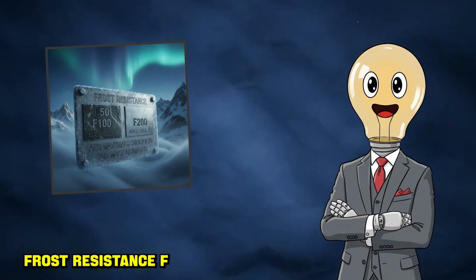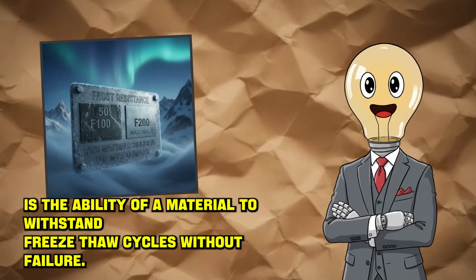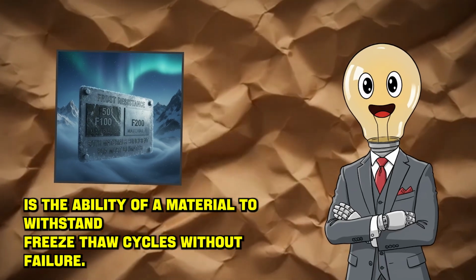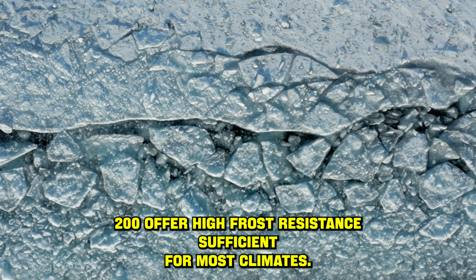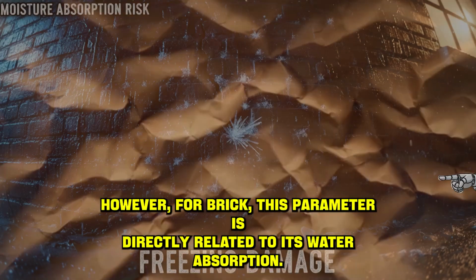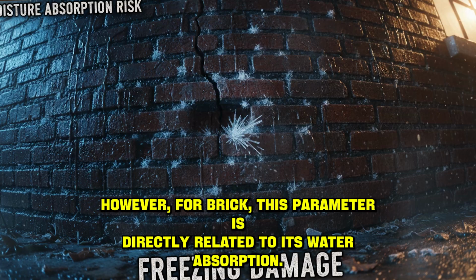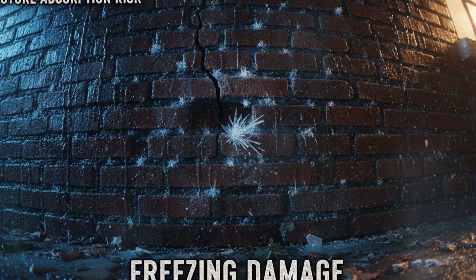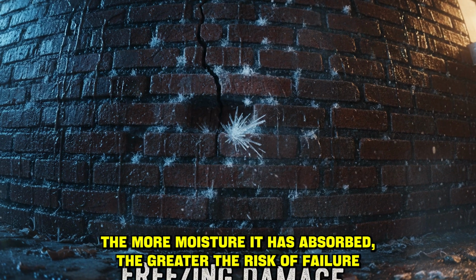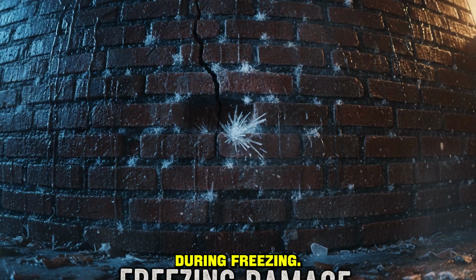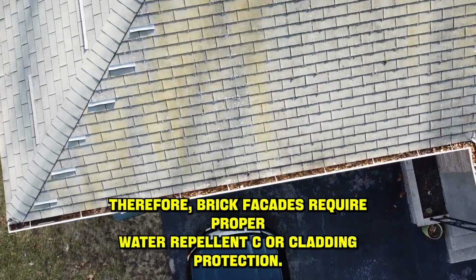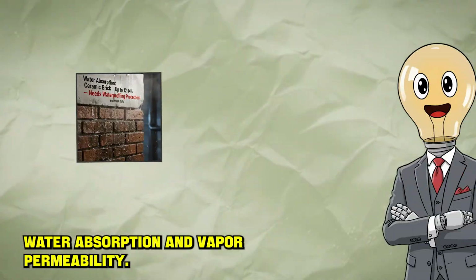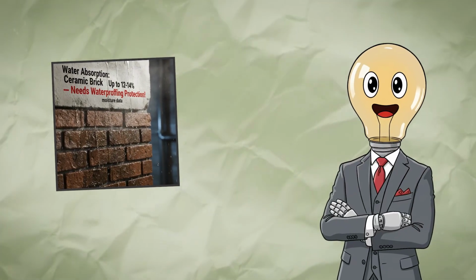Frost resistance, F, is the ability of a material to withstand freeze-thaw cycles without failure. Modern grades of both brick and concrete, F50, F100, F200, offer high frost resistance, sufficient for most climates. However, for brick, this parameter is directly related to its water absorption. The more moisture it has absorbed, the greater the risk of failure during freezing. Therefore, brick facades require proper water repellency or cladding protection.